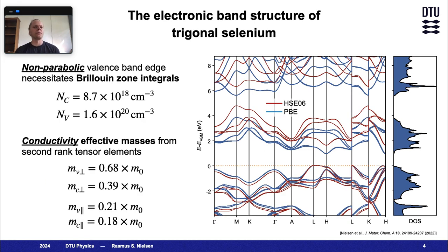If we take a closer look at the electronic band structure, the valence band edge is far from being parabolic. Therefore, to assess the effective density of states, we have to compute the carrier densities using Brillouin zone integrals, and from there evaluate the effective DOS. This also complicates the determination of the effective masses, as the masses relevant for transport are no longer equivalent to those derived from the density of states.